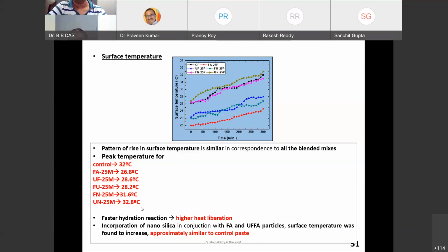That is what is asking the engineer in charge at the sites to go for best quality control practices and best curing systems. That is the need. We know why very well: with faster hydration reaction and increased nano silica in conjunction with fly ash, the ultrafine surface temperature was found to increase, approximately similar to control paste. That's what I was talking about.